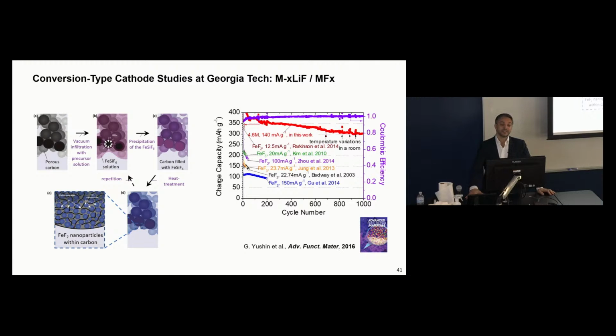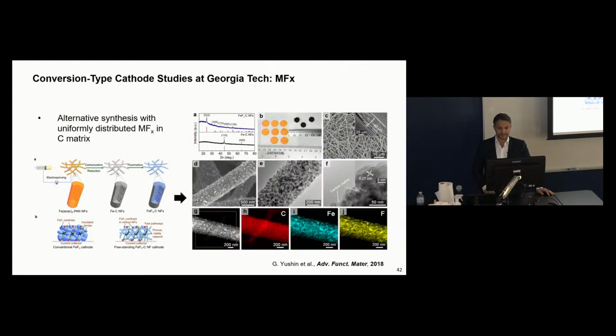And in this simple example, we nanoconfined these metal fluoride particles within activated carbon. In a very simple process, infiltrate precursor, convert it to metal fluoride. And so then you don't rely on metal to conduct electrons. You have this carbon matrix to conduct electrons, and you use this nanoconfinement in order to prevent ripening and phase separation between metal and lithium fluoride during cycling. And then, we demonstrated, quite some time ago, you can achieve hundreds of stable cycles at this high capacity.